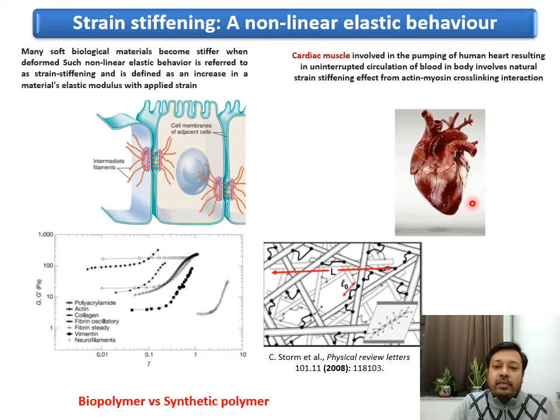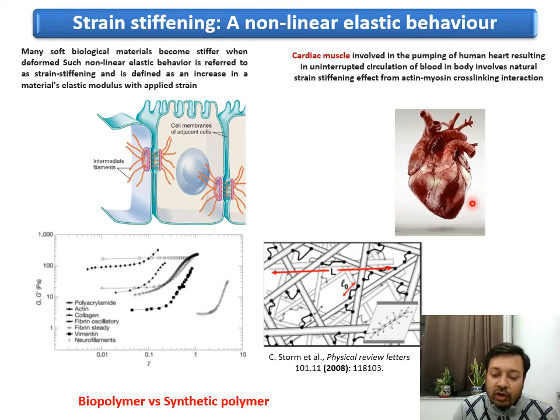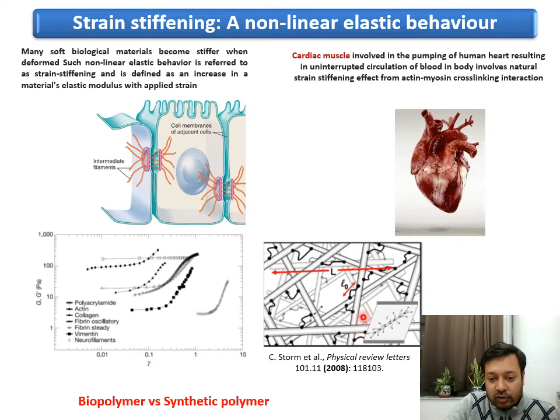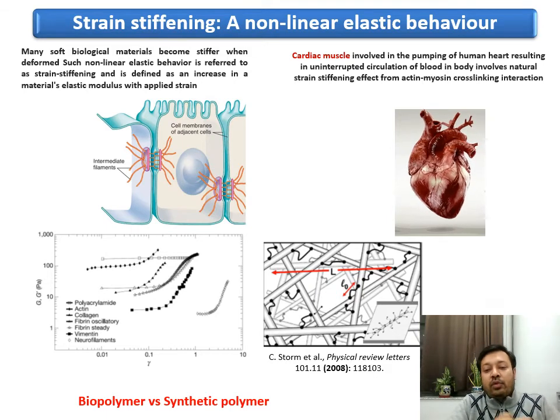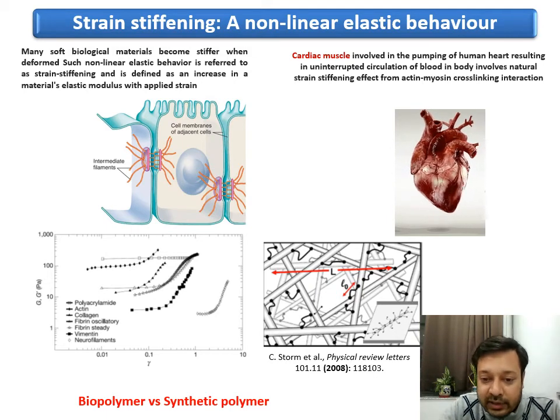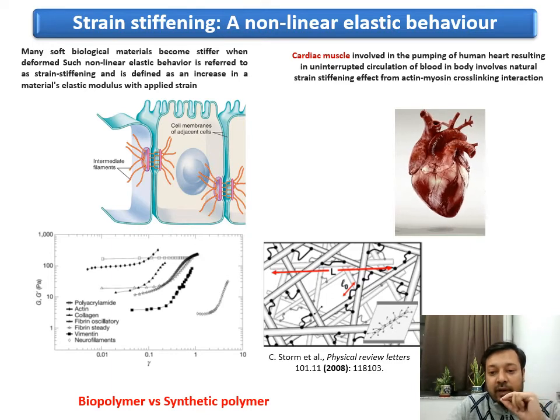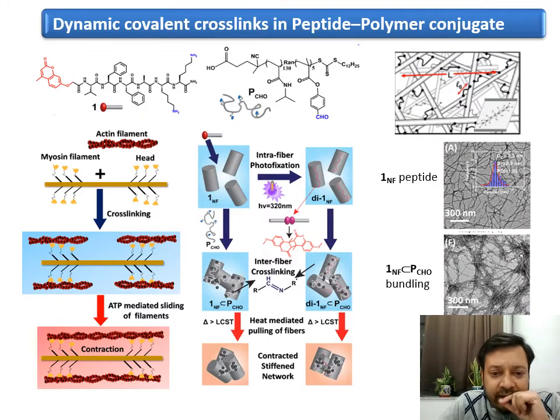But then how can you make a synthetic material out of it? So what we followed was a model which showed that if you can cross-link such rigid rods of fibers using a suitable cross-linker, then if you pull this entire network system, the rigid rod will give a strain stiffening response. This is what we see in a composite of actin cross-bridged with myosin filament. When this slides because of ATP mediation, it can generate such a contractile material, and it shows strain stiffening behavior.